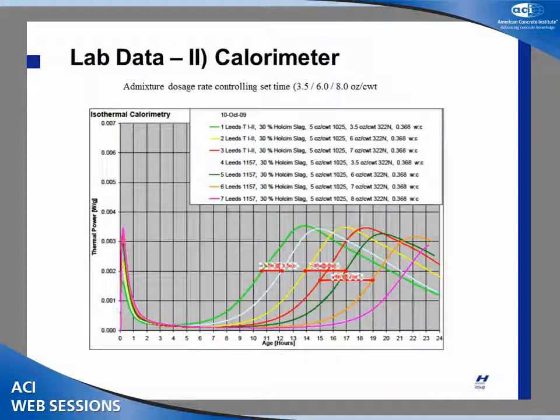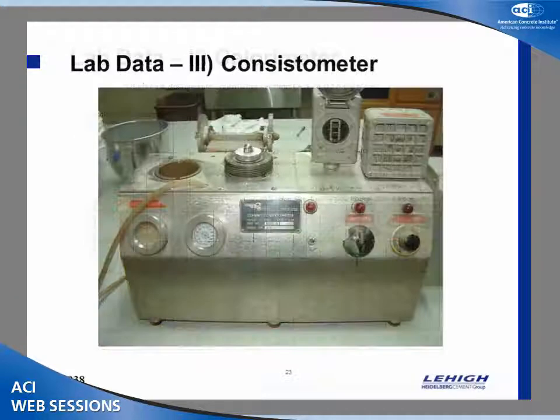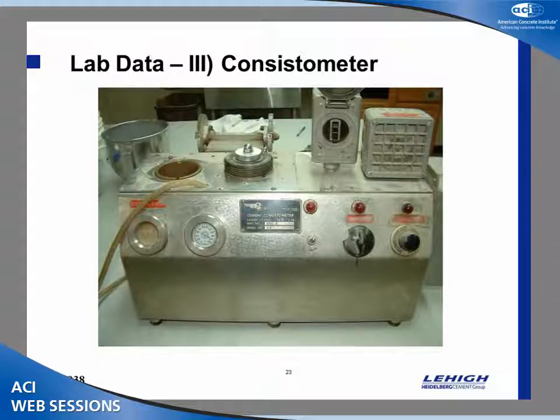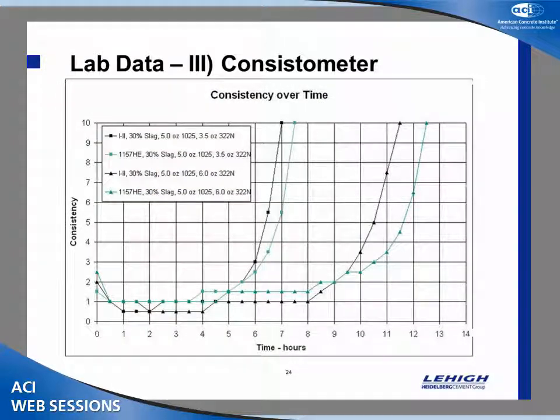Here's 30% slag with different amounts of admixture combinations. So you can see that we could very well control the set time of these different mixes. And we found an old consistometer, which is a precursor to a rheology type of testing. This is actually used for oil well cement, and we did some testing with this and came up with the stiffening. This measures the stiffening characteristics of the cement, right?